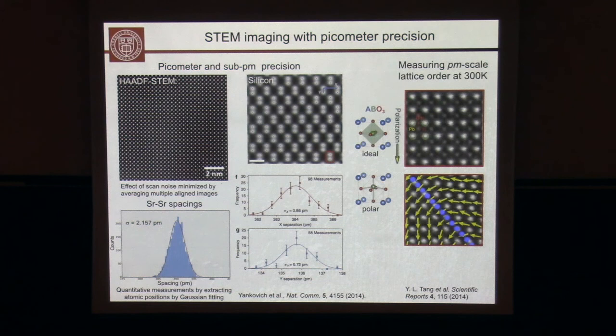Why is it important to extract this? So one system that is usually very intuitive to think about is if you take our perovskite oxide and displace the transition metal along one axis, you can get polar displacement in the material. And if we can extract this polar displacement, that gives us one order parameter that couples directly to the physical properties of the material. And that's what they have done here, where they have mapped the position of the A site cation, these are the bright ones, and the B site cations in the middle, and mapped out polar displacement and how they vary across domains. Okay? And this is a local probe, which is quite interesting.